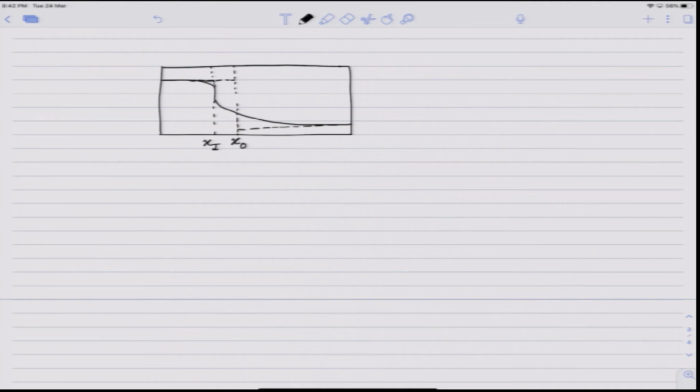On the left side I have alpha phase, on the right side I have beta phase. Obviously, as the diffusion progresses, one phase has to grow at the expense of the other, and hence the interface has to travel. So, it is important to know at what rate this interface is travelling, because that way we can estimate the growth rate of a particular phase.